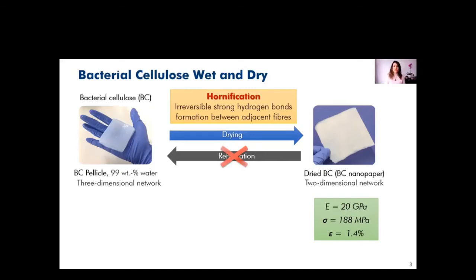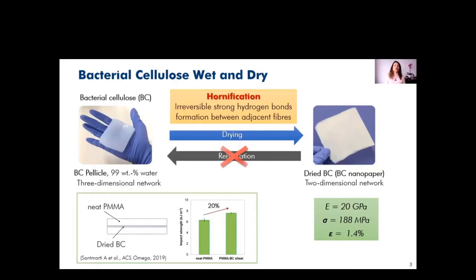For this reason, these bacterial cellulose nanopapers have been used as reinforcement material for different types of matrices. In our group, in a previous study, neat PMMA was reinforced with dry BC with one layer, and it was found that the impact strength of PMMA was increased approximately 20% using one layer of BC. But let's point out something here. The strain of dry BC nanopaper is really low, 1.4%, when we compare with commercial polymers, like in the case of polypropylene, that is 20%. So the question is, if the strain and toughness of the BC is improved, can that be reflected in the impact strength of the composite?